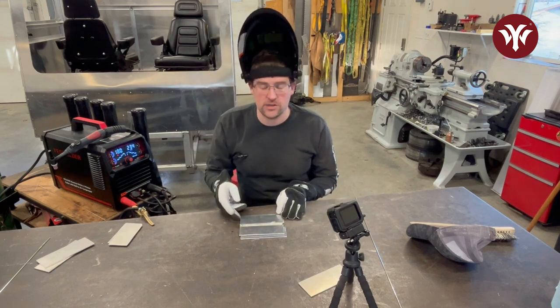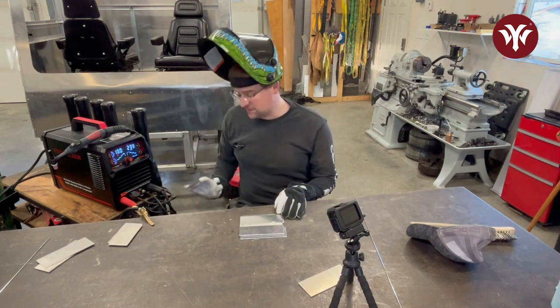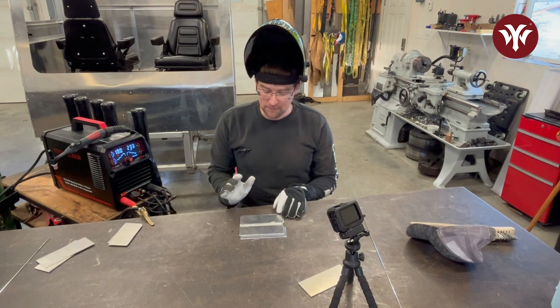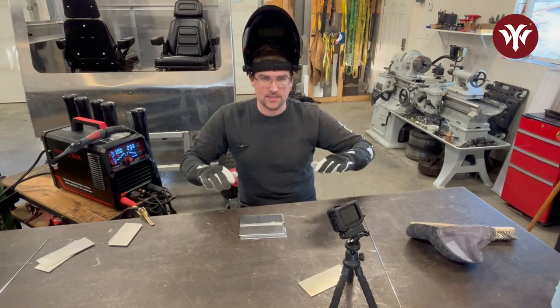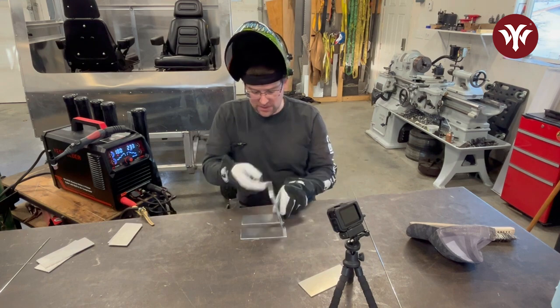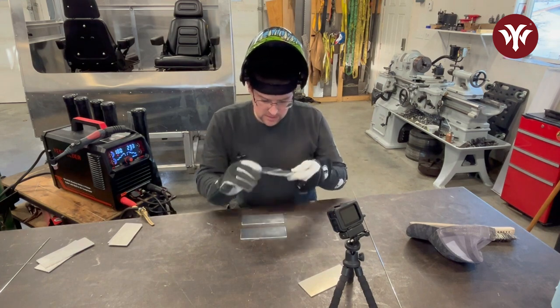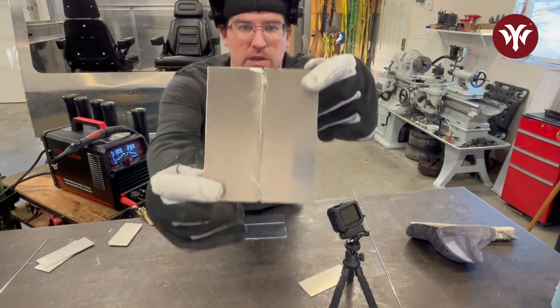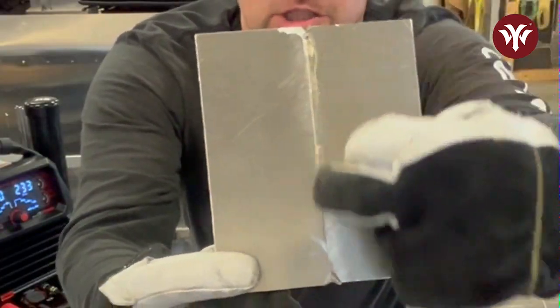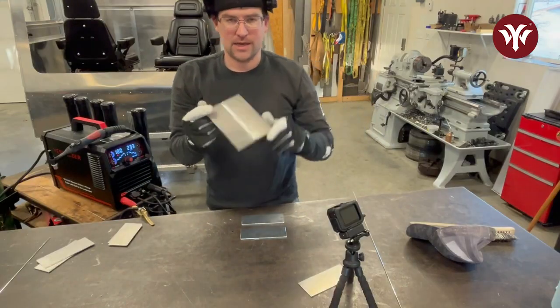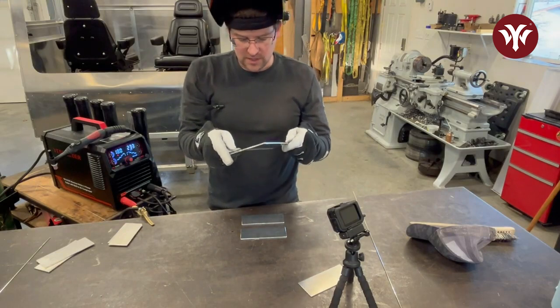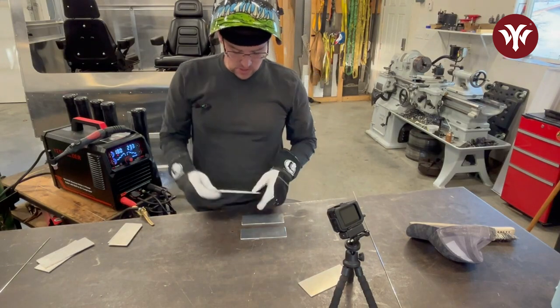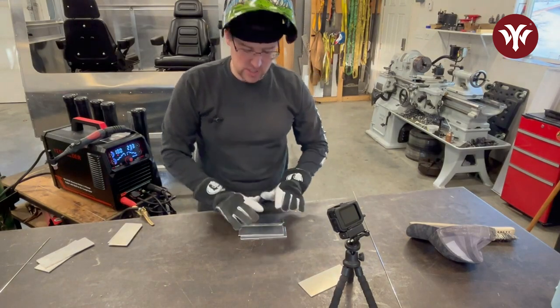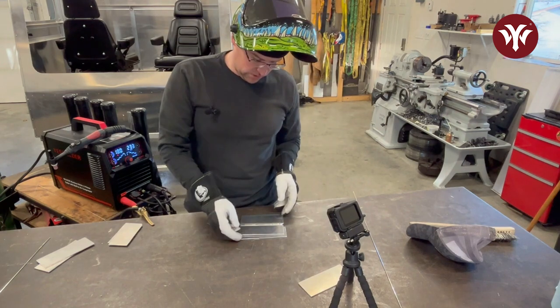Alright, so first thing I already noticed from that, I felt like I was getting approximately the same amount of current, but the weld flattened down, which means it was sinking in more, penetrating a bit more. And I'll show you here, it's really hot, but you could see I was starting to see that penetration come through the backside. So again, that right there shows you that's something you gotta pay attention to. You gotta pay attention to the material you're welding on and how much heat it's pulling away from your part.